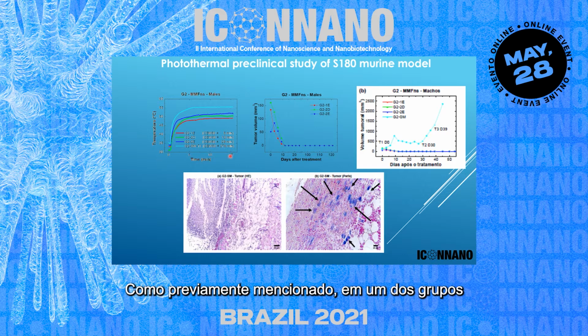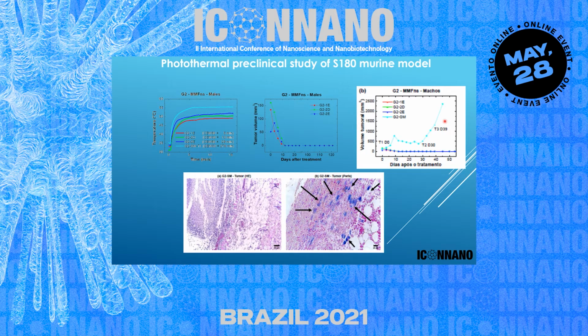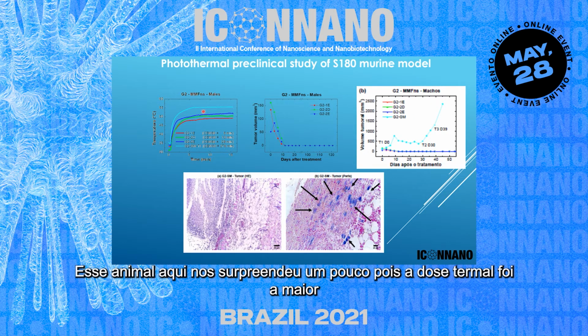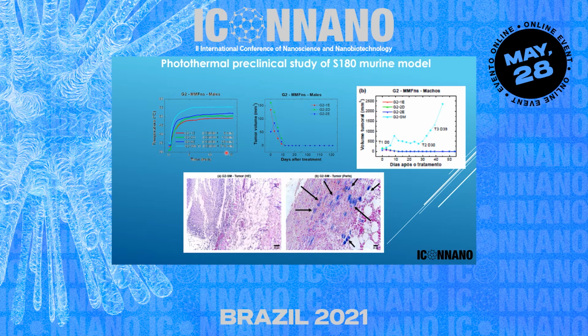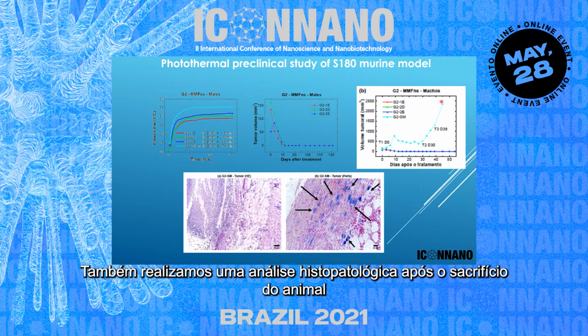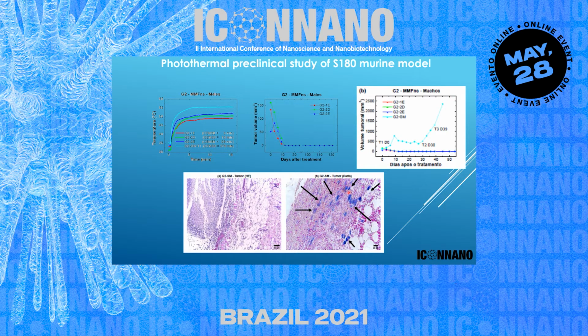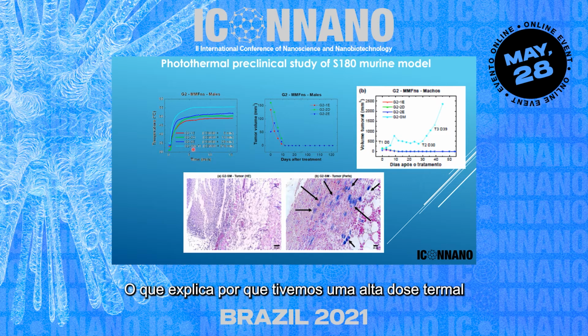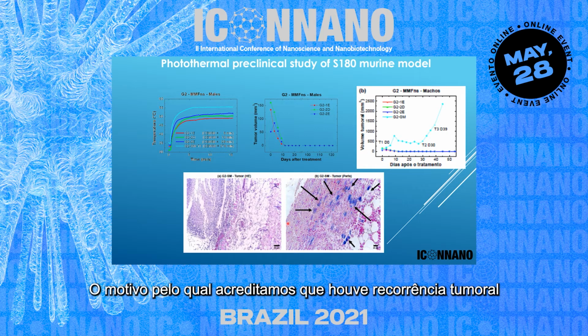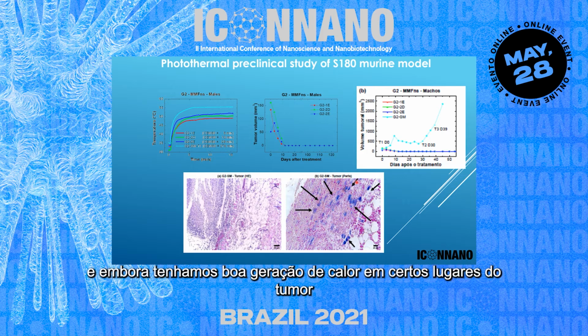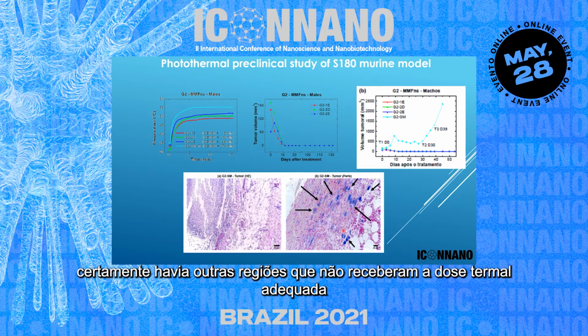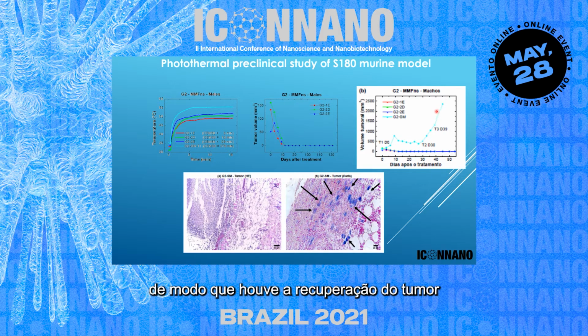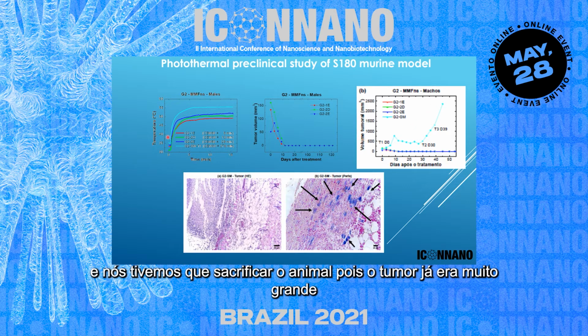So as mentioned before, in one of the groups, we noticed that there was a tumor recurrence. This animal here surprised us a little bit because the thermodose was the highest in this group. We also did an histopathology analysis after we sacrificed the animal. We did observe that there were nanoparticles there, quite a lot. That explains why we had a very high thermodose. And the reason why we believe that this animal showed tumor recurrence is that tumors are actually heterogeneous, and although we had a very nice heat or temperature increase in certain places in the tumor, there certainly were other regions because of the heterogeneity of the tumor that did not receive enough thermodose to kill the tumor cells, and that's why it recovered, and eventually we had to sacrifice the animal because the tumor were very large.